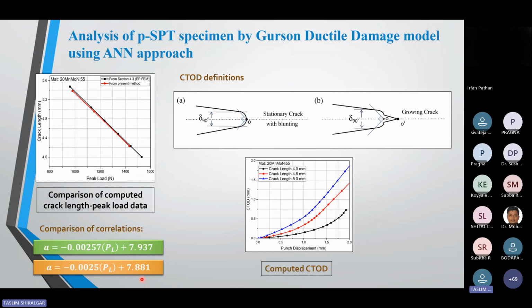But can I use the similar code to get the CTOD from these specimens? So I started working on this. Is there any CTOD approach available for a growing crack? I studied all the papers and observed that this methodology is not available for a growing crack. I would like to tell you more information.